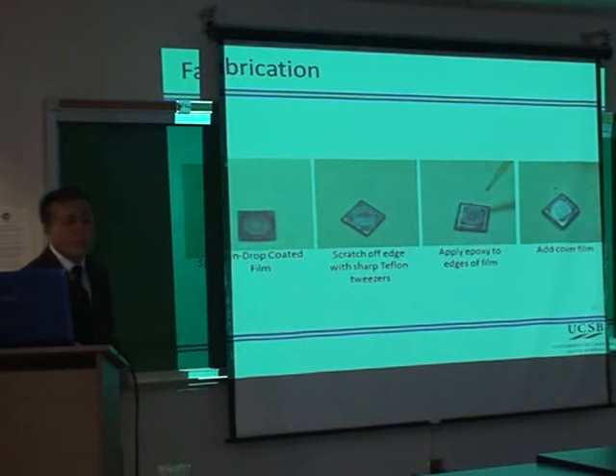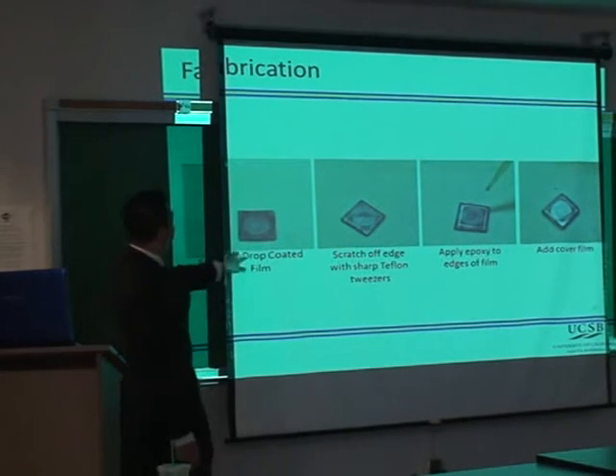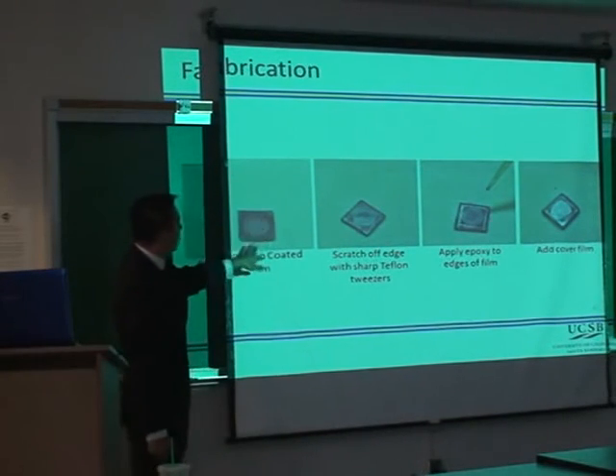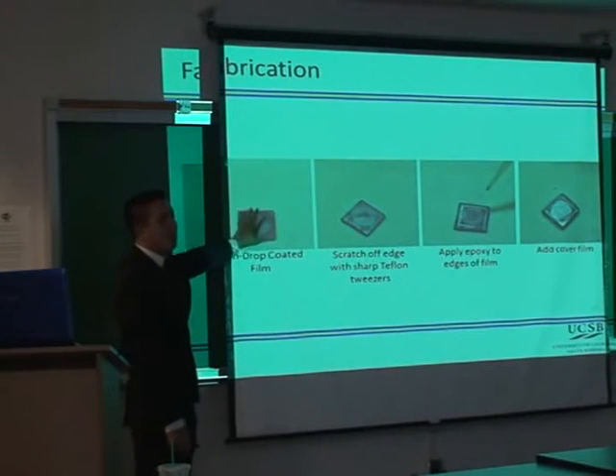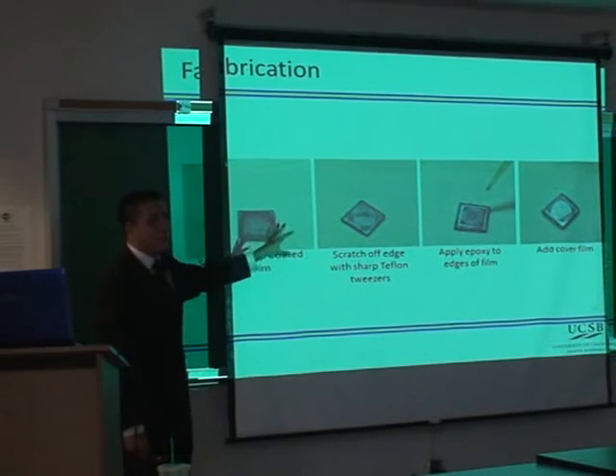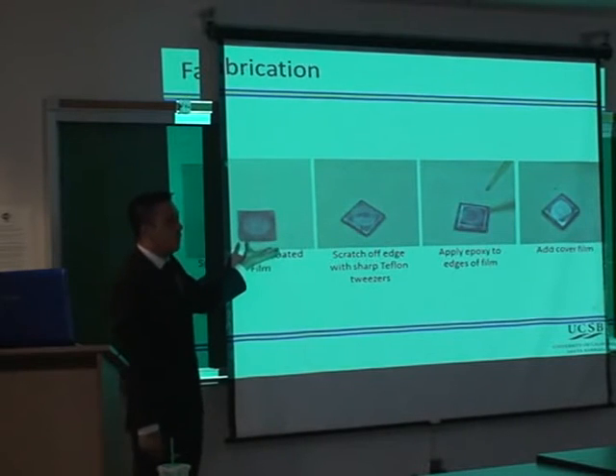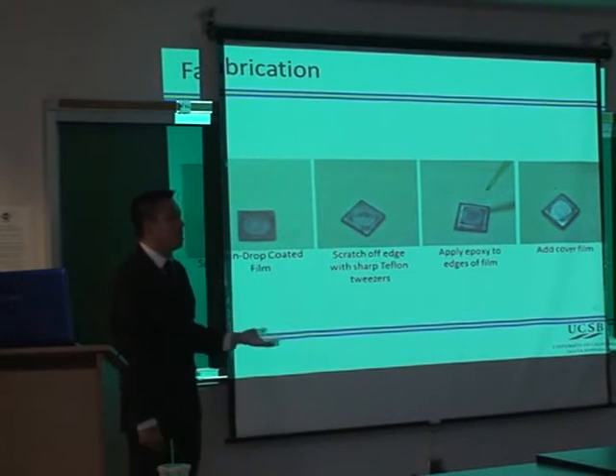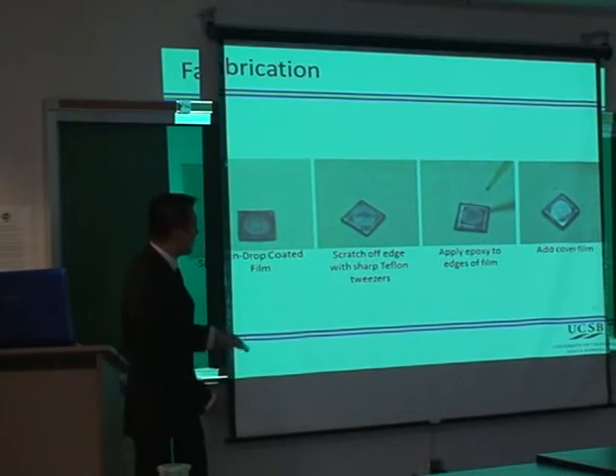So the first step was fabrication. So we have our quartz substrates, and we spin coat them. And these are actually quite small. These are actually smaller than a penny, which kind of made them difficult to work with. And the reason why we had to do that is because we didn't have a lot of material. And some of these materials are actually very expensive and require a lot of work to synthesize.